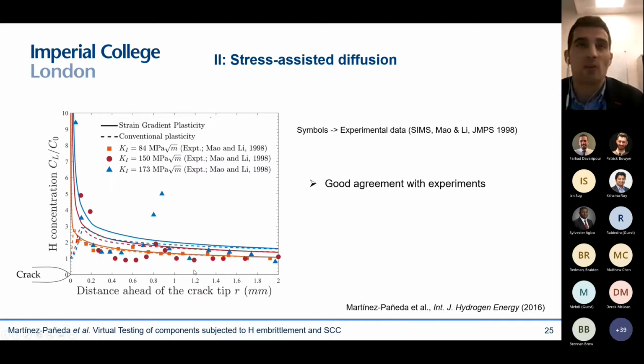And we have tried validating this with experiments. It is difficult to find experimental data at such short distance ahead of the crack tip, but there are some. And the agreement is very good, which is very promising. And basically what you can see here is that only by accounting for those dislocation hardening mechanisms, one is able to capture 2 things that you see in the experiment.